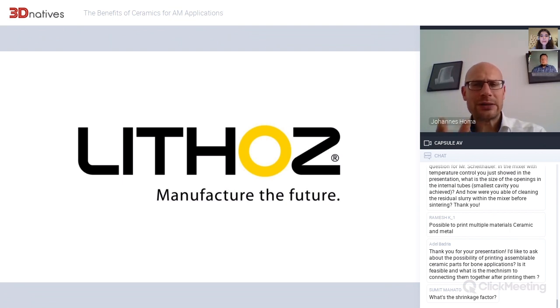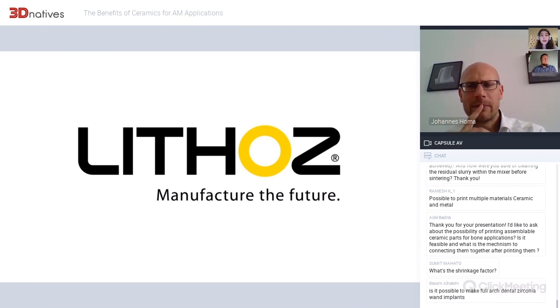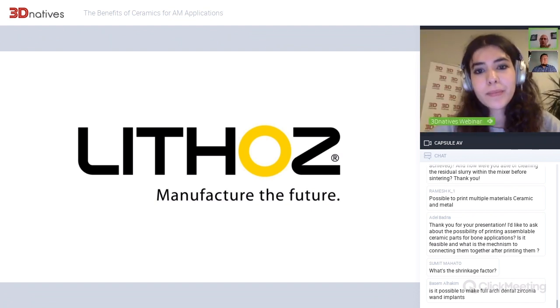And the first question was? It was actually about Lithoz technology, the resolution of your technology. Yeah, there are different resolutions available, from 25 microns to 75 microns. But it depends mainly on your application which resolution you would need. This is not the limiting factor. We have seen that most of our applications, or the surface roughnesses I will show you, were all printed, for example, with 40 micron resolutions.